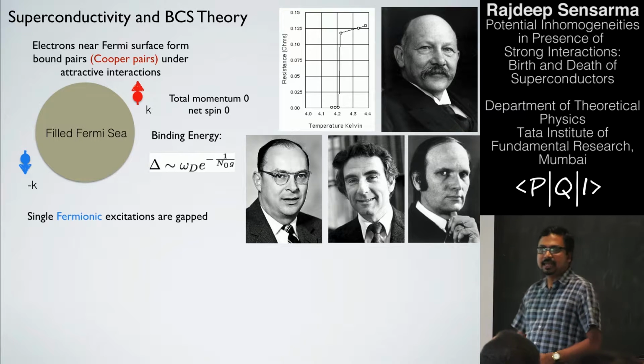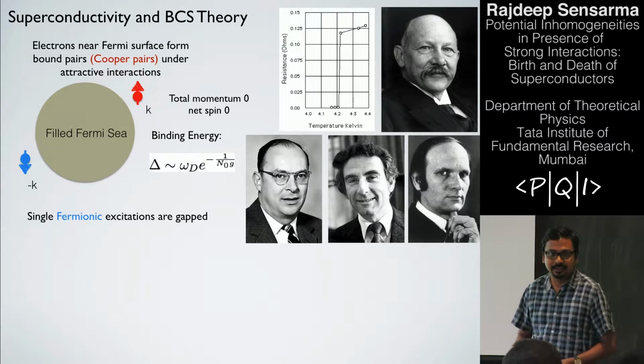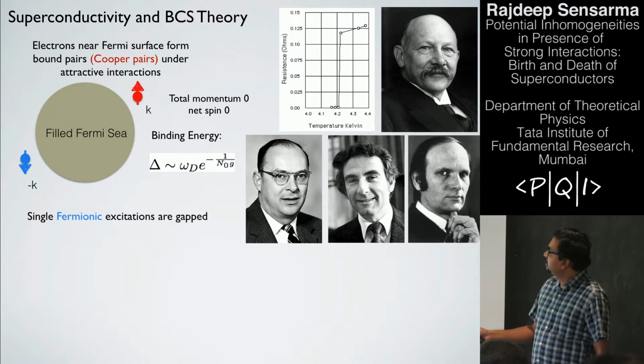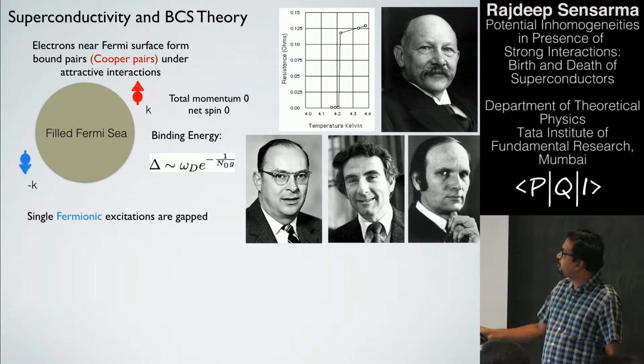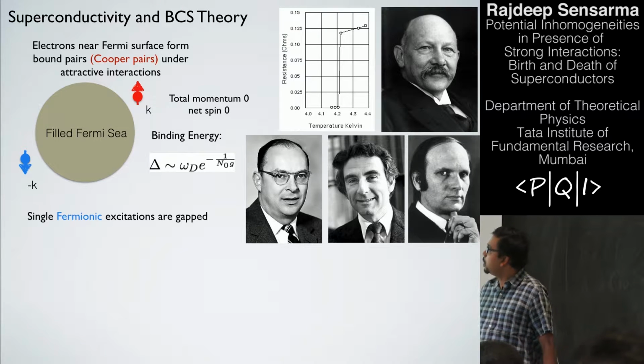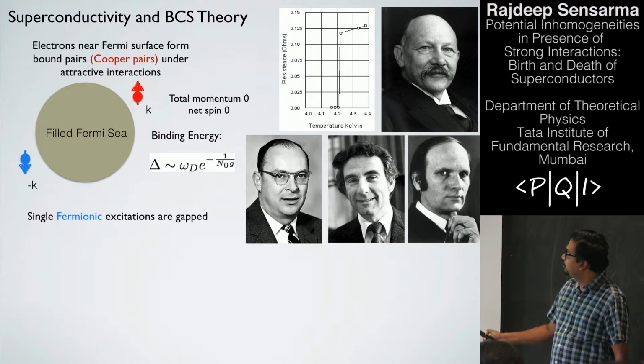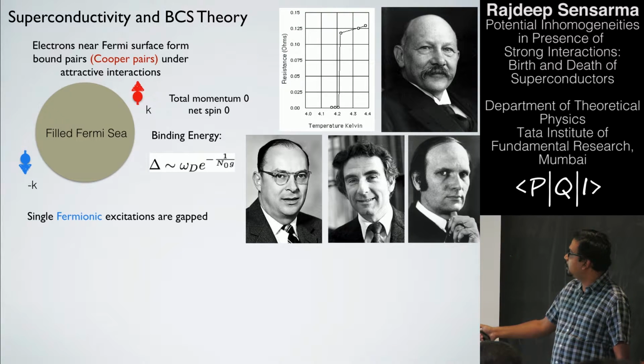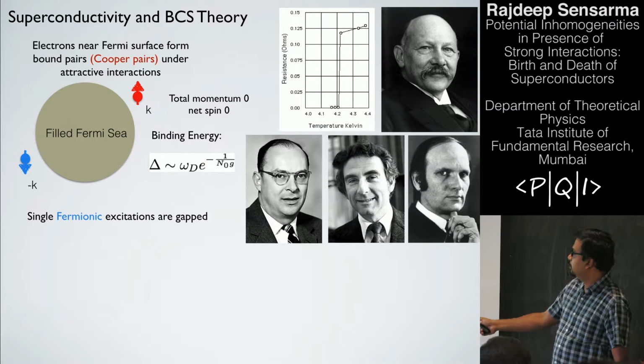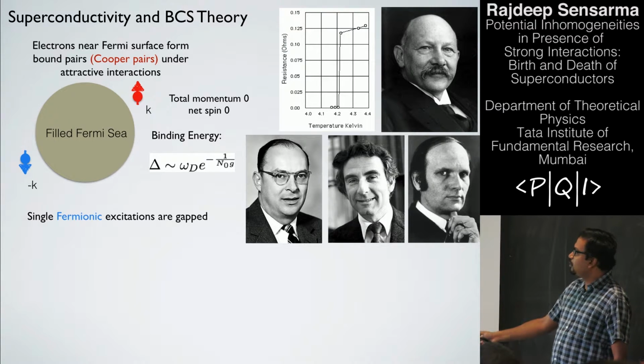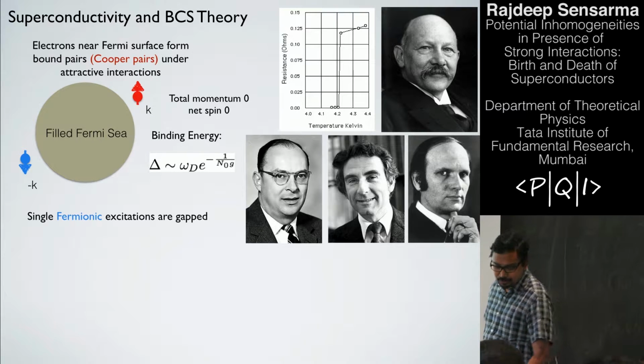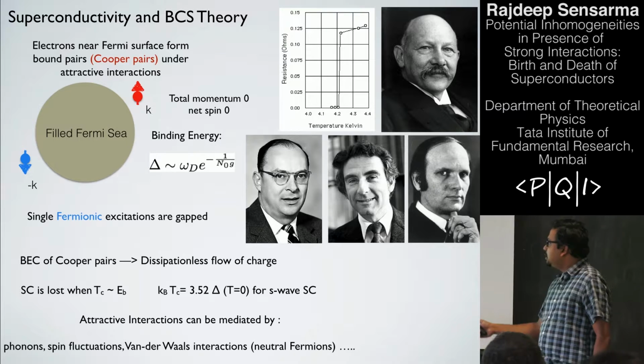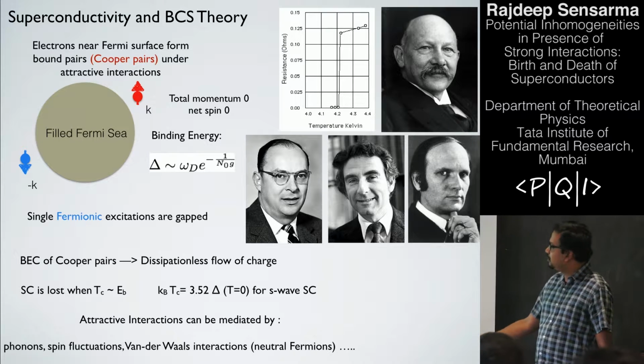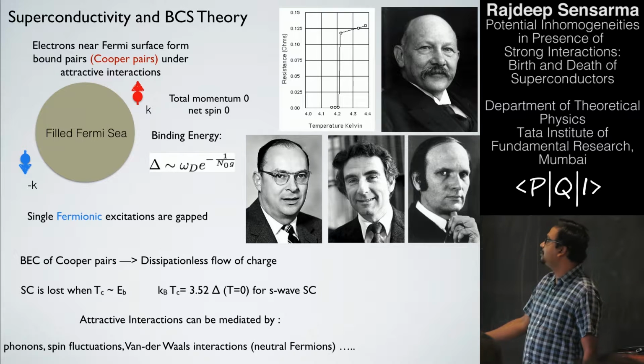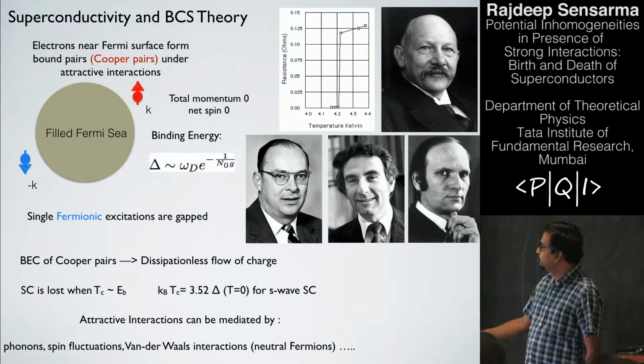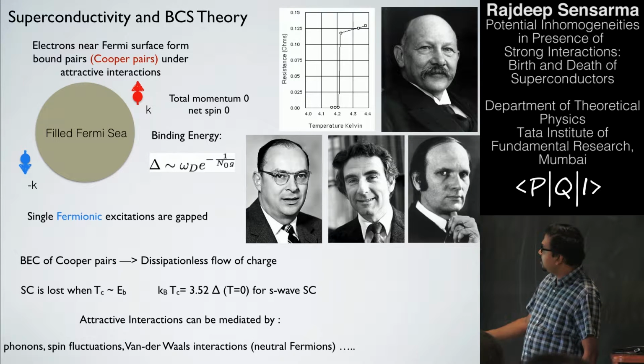What happens is that the electrons somehow feel an attractive interaction with each other. And when that happens, in the presence of a Fermi sea, the electrons form bound states. They're called Cooper pairs, with total momentum 0 and net spin 0, with a binding energy which is a non-perturbative function of the coupling constant. But then, since the electrons are bound, the single particle excitations are gapped. But the pairs, which have some bosonic characteristics, can form a BEC of Cooper pairs, and this leads to dissipationless flow of charge. This is nothing but superconductivity.